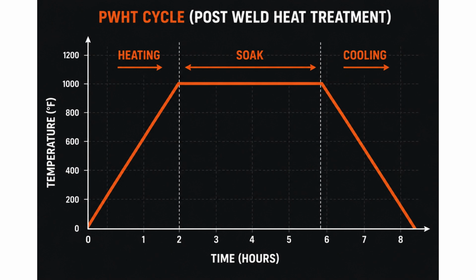So what's actually happening in the furnace? 3 phases, tightly controlled. Heating. Above 800 degrees Fahrenheit, the rate is capped, generally scaling down as material gets thicker, so you don't shock the metal. Soaking. The vessel holds at the specified temperature for a specified time.